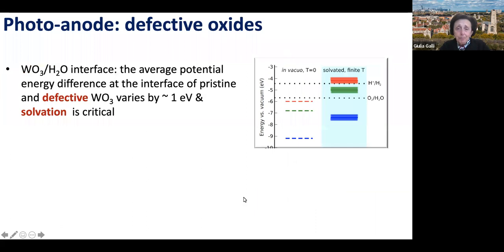When we went to oxides, and one oxide that we studied extensively, tungsten oxide, one thing that we really understood, and of course other people studied that and pointed out for other surfaces, like Annabella Selloni for titanium oxide and Mike Hybertsen and Marivi Fernandez-Serra for other oxides like zinc oxide, is that defective surfaces are what you have. You never have a completely clean surface, like in the case of silicon, for example. In silicon it can be done experimentally, but all oxides are defective and they have oxygen vacancies. And you have to take into account these defects, otherwise you will not understand what's going on.